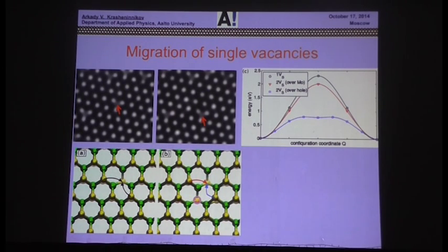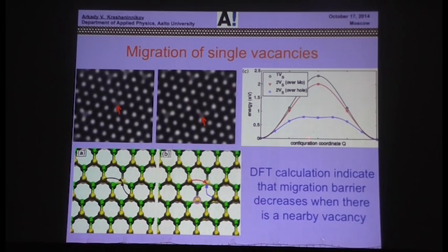However, if you assume there is a vacancy already nearby, this atom is missing, and calculate the barrier, it will be much, much smaller than in the first case. This essentially means that the concentration of vacancies increases. At some point, the crystallinity becomes unstable with respect to a pretty quick transformation to a lower energy configuration. And this is very likely, at least we believe, what happens in experiments when the concentration of electron beam-induced vacancies increases.